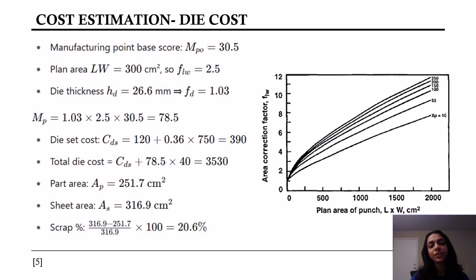Now we calculate the total die cost by multiplying manufacturing effort with the cost per point, where here we have $40 per point. So the total die cost comes out to be $3,530. We also analyze the material efficiency, where the part area is 251.7 centimeters square and the sheet area which is required is 316.9 centimeters square, which gives us a scrap rate of 20.6%.